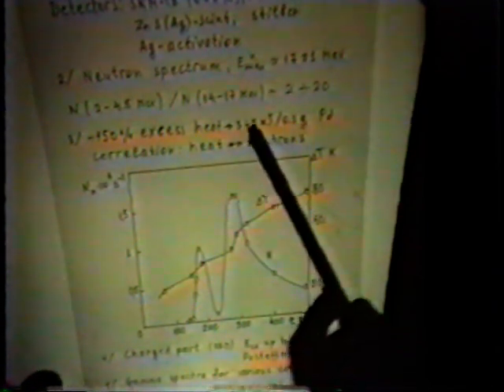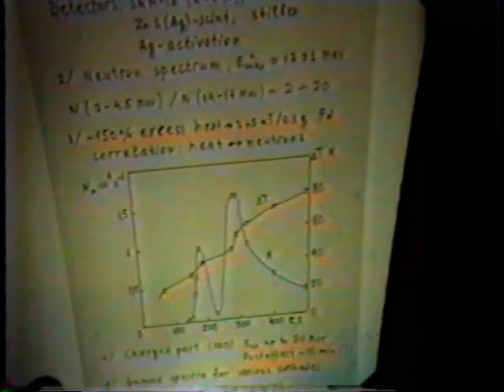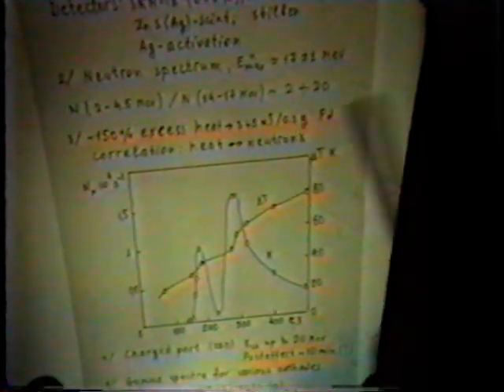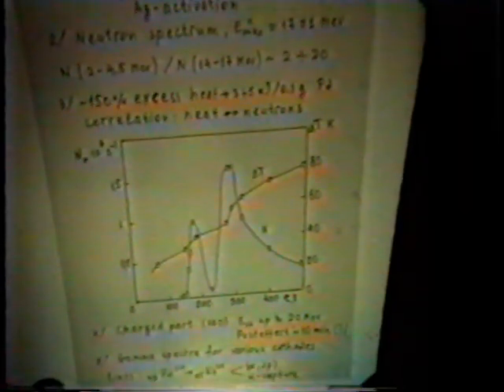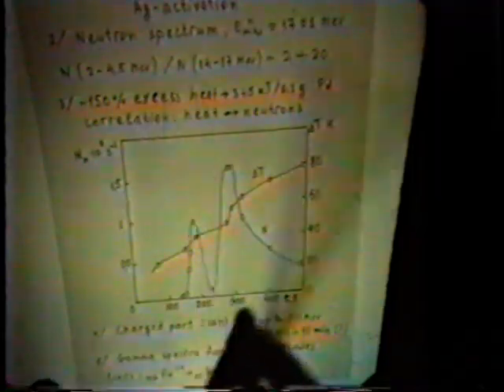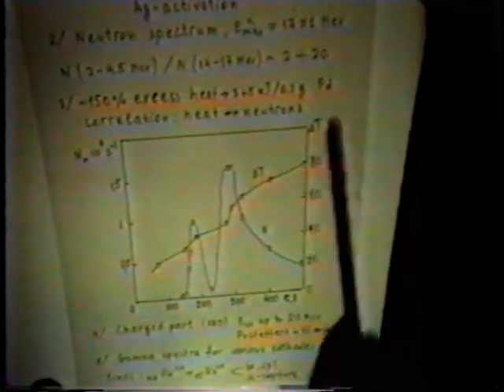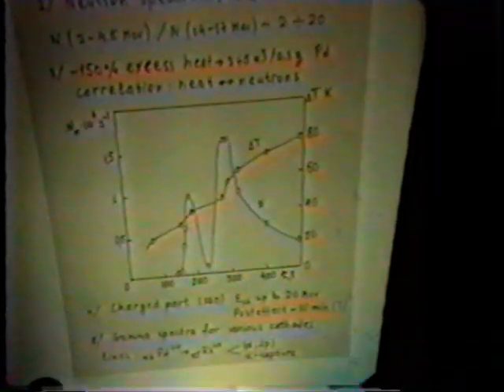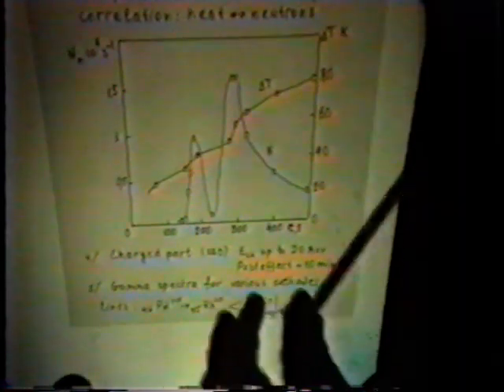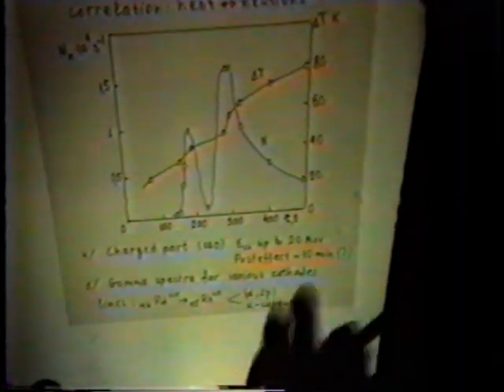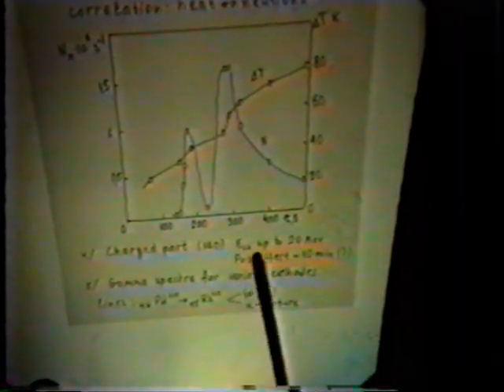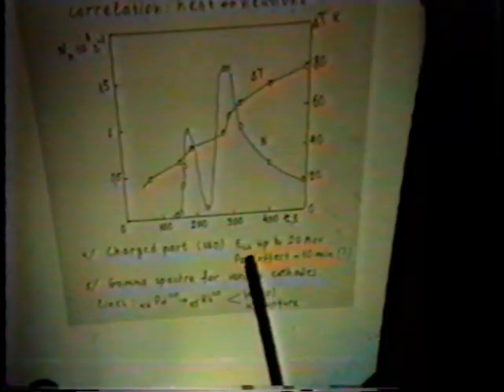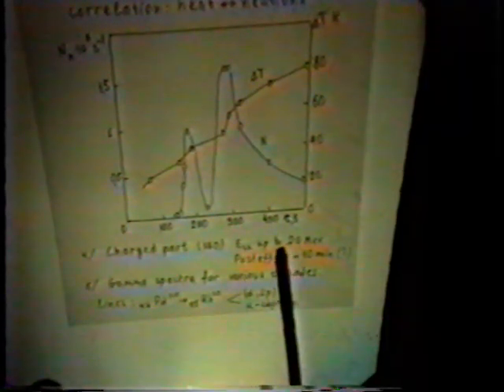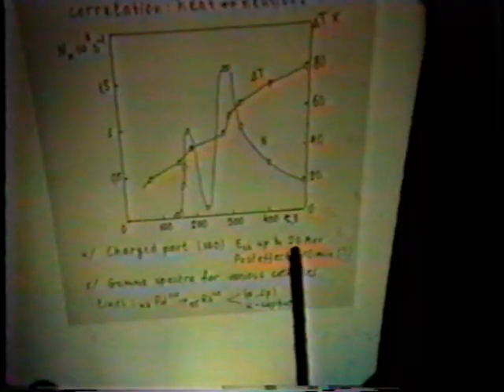which corresponds to about 3 to 5 kilojoules per 0.1 gram of palladium cathode. They also observed some sort of correlation between heat and neutron production, which is illustrated in this picture. They measured the charged particle spectrum, and they observed an upper limit for the energy of charged particles of about 20 MeV.